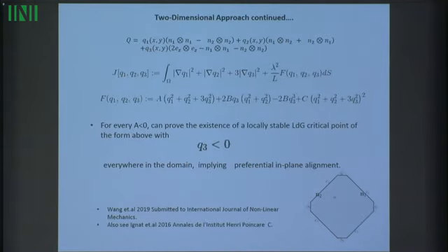Well, yes, they do. And you can study these reduced critical points, with just 3 degrees of freedom, as being critical points or minimizers of this functional that I've written up there. This is effectively just the Landau-de Gennes energy of these critical points. If you look at my formula, you will see a lambda. The lambda is the size of your domain, it's the size of your square effectively. The L is your fixed elastic constant. Now in this work we haven't actually played much with L, it's treated as fixed. And then the rest you've seen. The A is your temperature, and the B and the C are fixed material dependent constants.